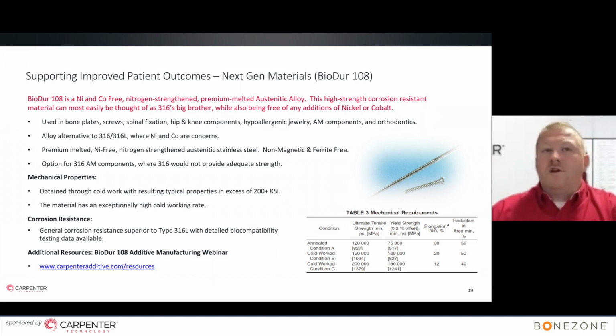As Gaurav mentioned earlier, nickel sensitivity in the United States is estimated between 12 and 15% for the Center for Devices and Radiological Health. And exposure to that nickel could come from normal wear and tear of medical implants, and that can lead to adverse side effects. With Biodur 108, we can collectively offer implant materials that have both producibility and workability similar to a 316 LVM, but without the concern of cobalt and nickel contents.